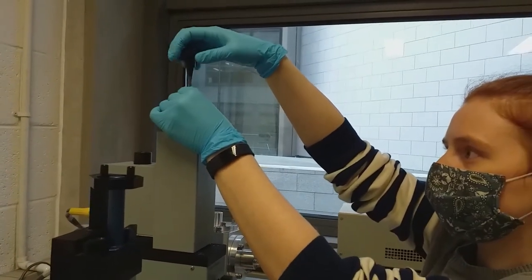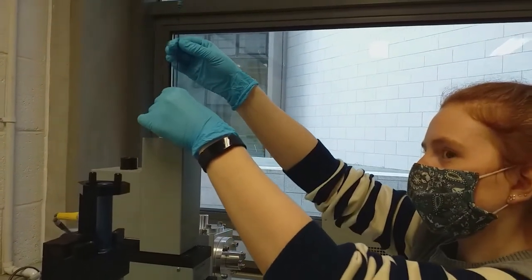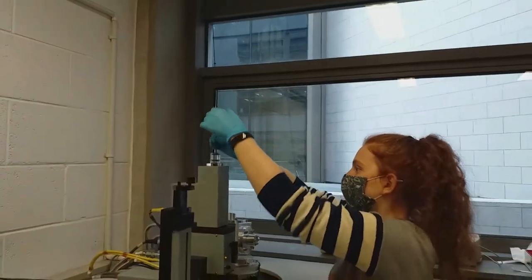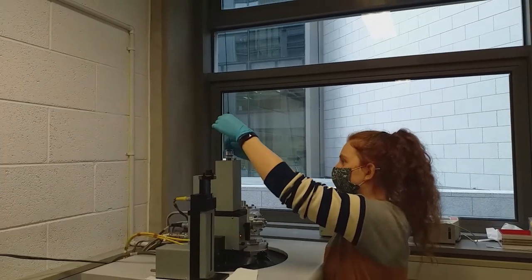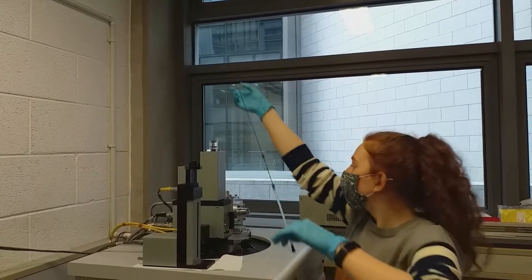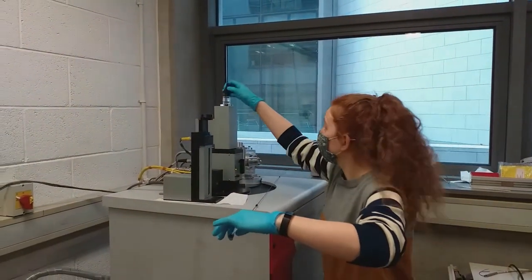Once it is ready, I can remove the cap and slowly pull the rod out. As you will see, we attach the plastic straw containing our sample to the end of the rod. There will be an additional diamagnetic contribution from the substrate on top of the signal from the thin film sample. At the end, we have to correct the data to remove this contribution. And don't forget the cap.